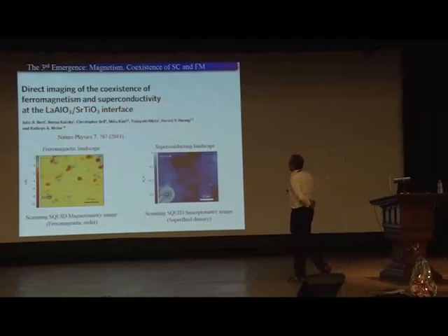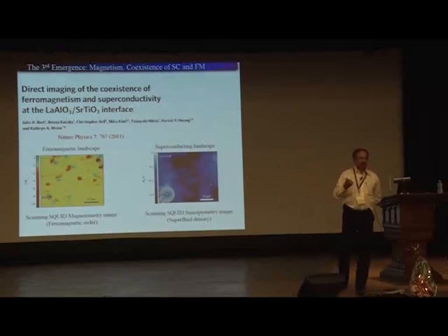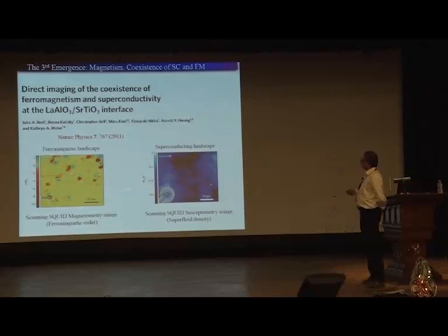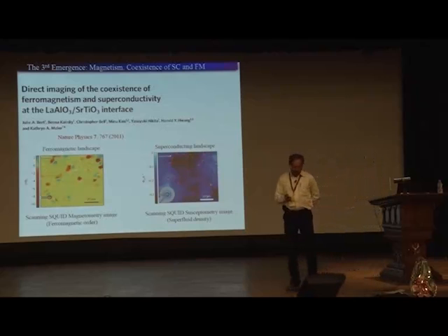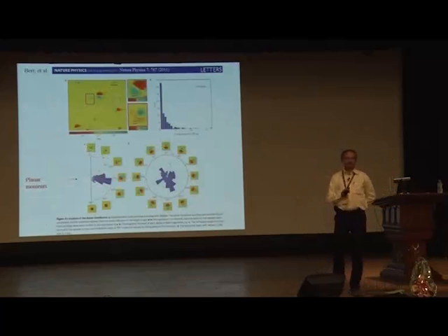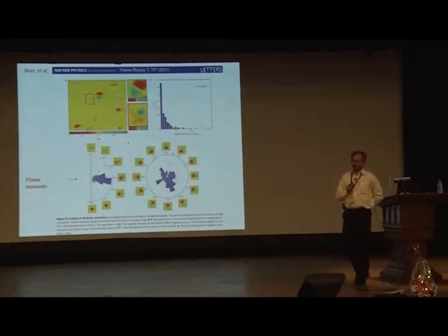So this was emergence of magnetism, coexistence of superconductivity and magnetism. As I heard from him, there are systems and samples where you don't see it, and there are many samples where you see it. The samples reported here had both superconductivity and ferromagnetism, and this is the landscape. There are regions of ferromagnetism and superconductivity, both distributed in a patchy way. The other interesting thing is that the moments are highly planar. There is almost no z component to this moment around the 001 direction.